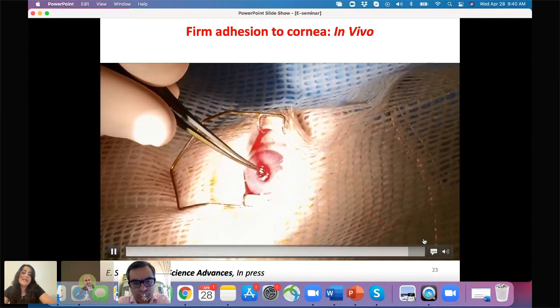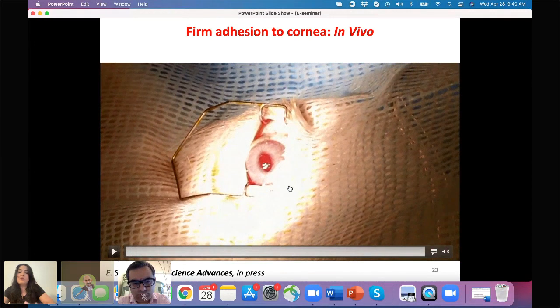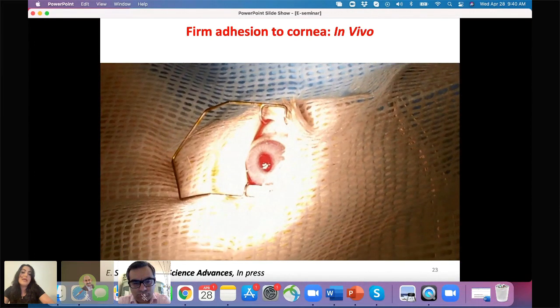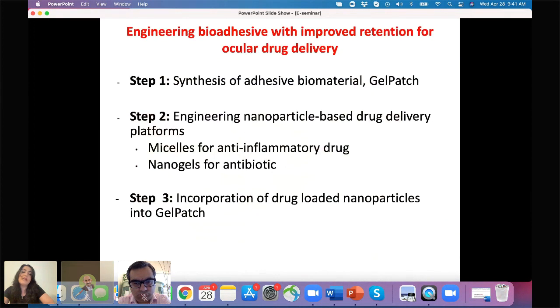So with this paper, we show that GelCORE has tunable properties. It can be used to seal stromal defect on the cornea. However, when we are dealing with larger size defects like laceration, and also when the eye is inflamed or infected, GelCORE is not effective. So in the next step, we designed a new formulation of the bioadhesive with improved retention for ocular drug delivery.